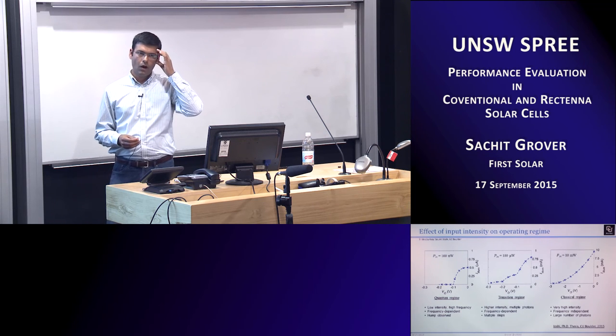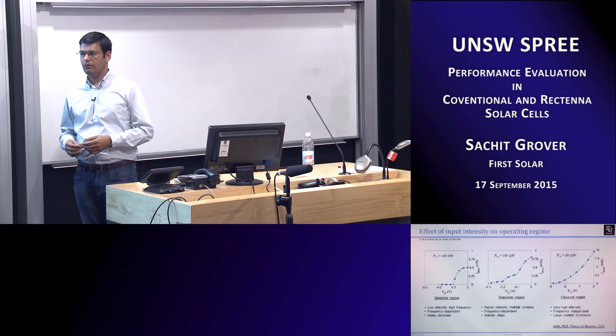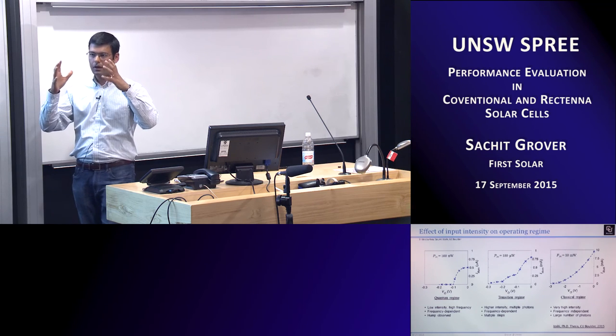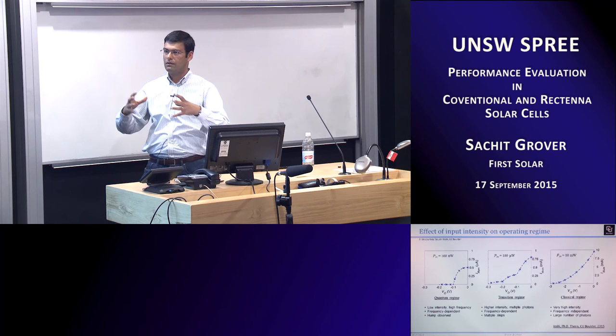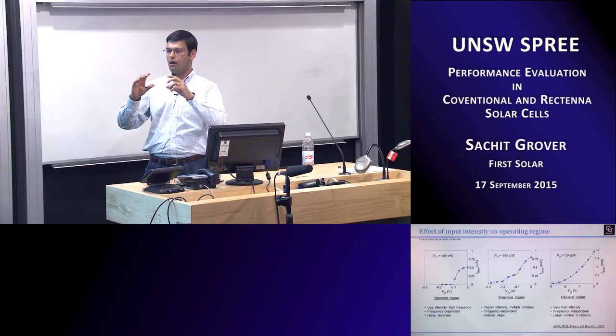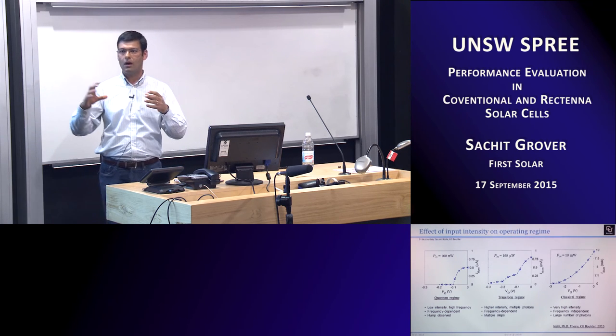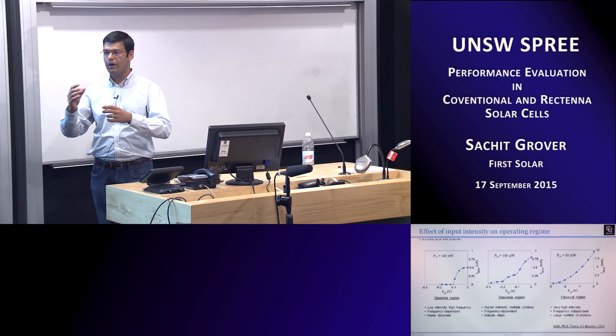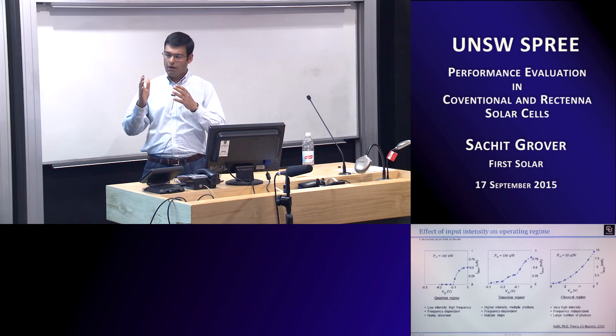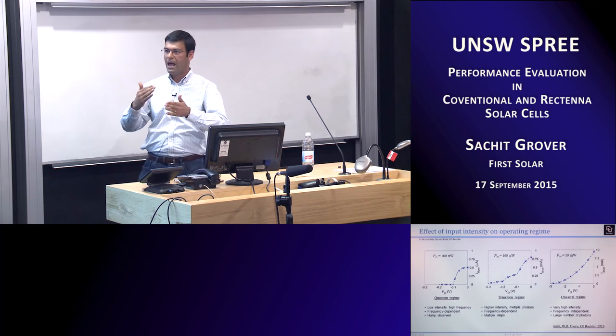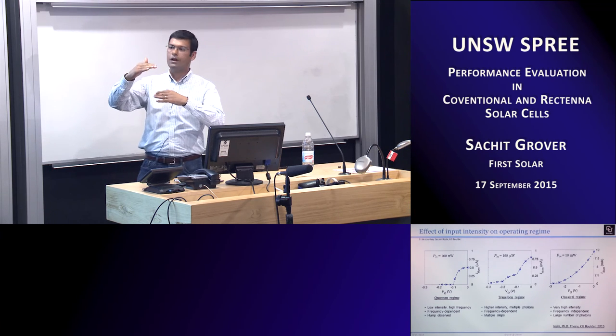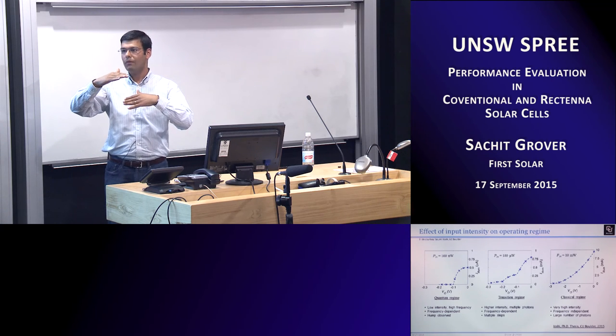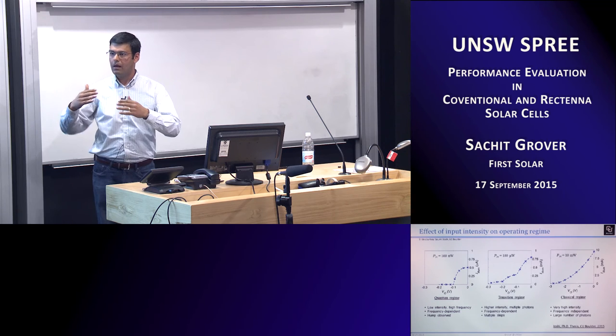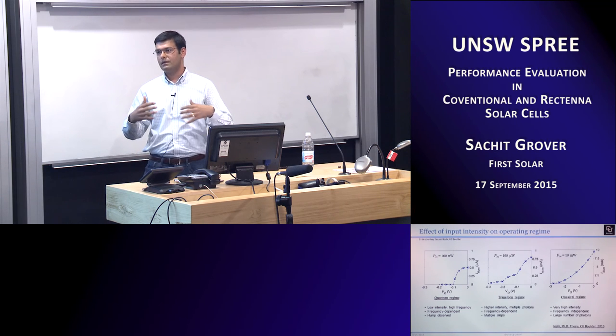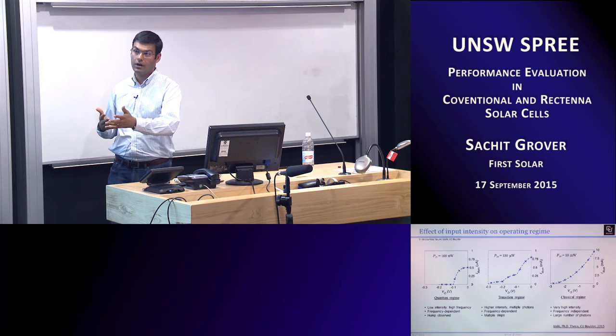I'm not very familiar with the physics of OPV, but to get you thinking along the lines that I was thinking when I developed this, each recombination process has a thermal activation. The bulk and the space charge recombination are thermally activated across the band gap, whereas for the interface, due to the interaction of states at the interface with one of the bands, the energy across which the thermal activation happens is less than the band gap. That's really the key to this analysis. So I'm not sure if you can do the same with OPV.